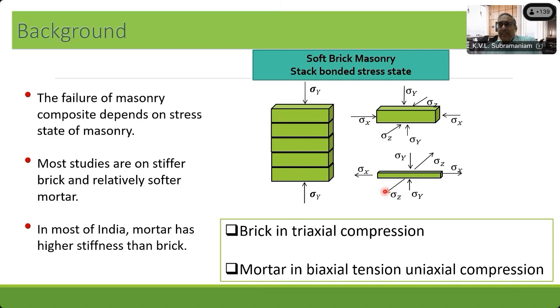The lateral stresses develop in the brick and the mortar because of these different properties of the materials. Whether the brick is stiffer than the mortar, or the mortar is stiffer than the brick, you will end up creating what we call a multi-axial state of stress in both materials, brick and mortar, although the applied stress is purely uniaxial. So this is the complexity.